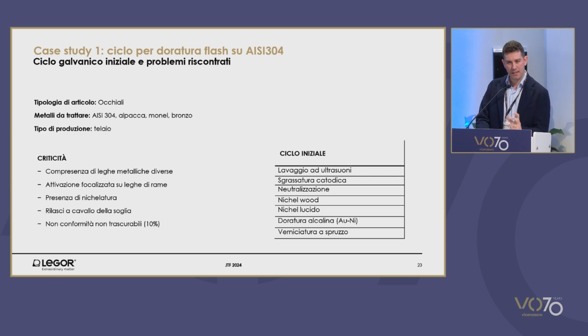Before the project was carried out in Legor, the client was too much focused on copper. At the beginning of the cycle, nickel was used, nickel wood, which is a chloride nickel, and then nickel deposition was often resorted to make the object resistant to corrosion, but the barrier effect, preventing the release of nickel after electrodeposition, was only relying on the spray cycle.